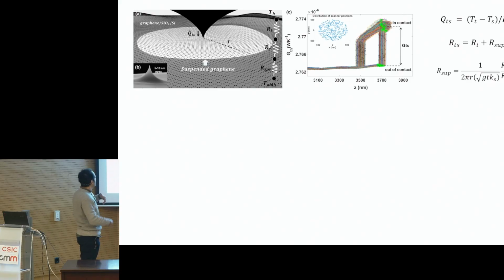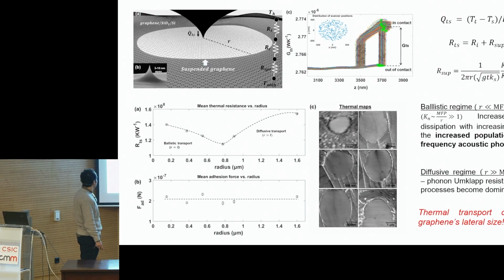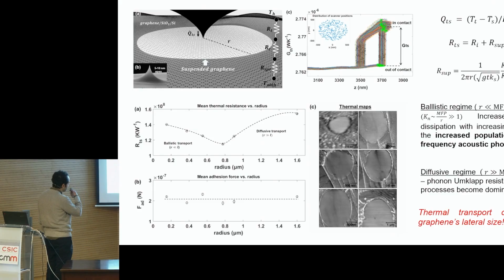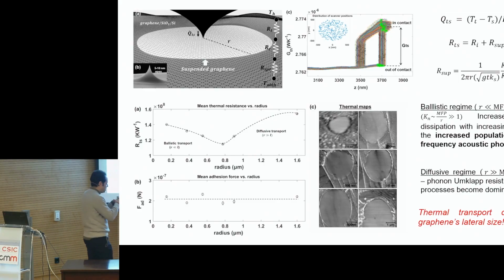And this is the model where we can extract the thermal resistance of the graphene itself. Here you see that this thermal resistance first decreases as a function of the radius, and then you see this crossover, and again the thermal resistance is increasing. When the graphene flakes have a radius much smaller than the phonon mean-free path in graphene, we have increased heat dissipation due to an increased population of the low-frequency acoustic phonons. So here we are in this regime.